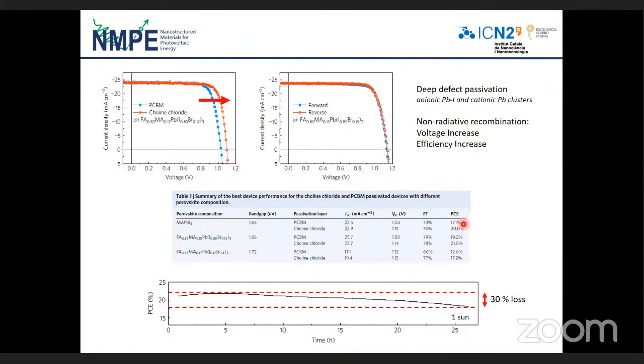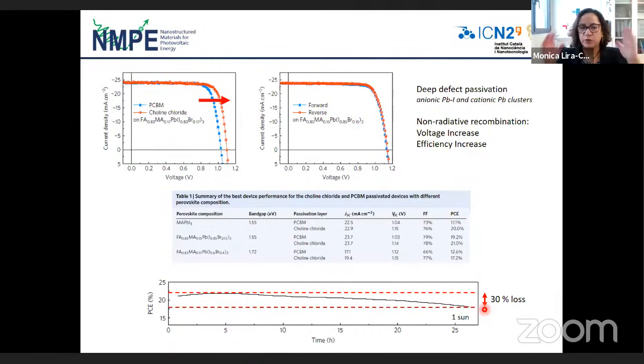However, we observe that not always do you obtain an increase in stability. We have in mind that as long as you increase efficiency and voltage, you are passivating defects through non-radiative recombination, eliminating this recombination, and then you should have stable solar cells. Usually when you do this, you obtain better stability than the solar cell without the additive. But not always does it result in a very stable device. Here, for example, you can see that in only 25 hours under light irradiation, under constant irradiation, you already have 30% efficiency loss. So this is not a very stable solar cell. However, the voltage and efficiency again were very good.